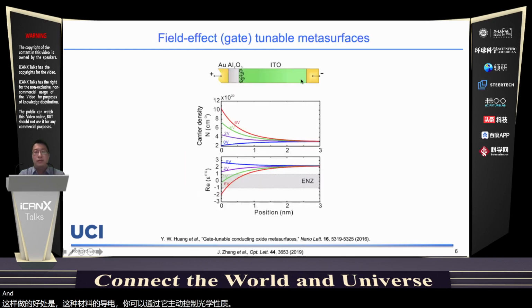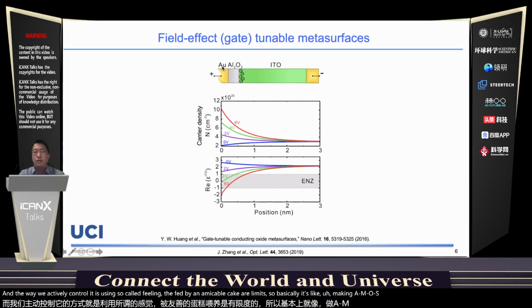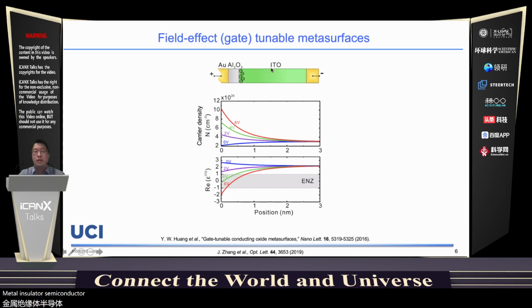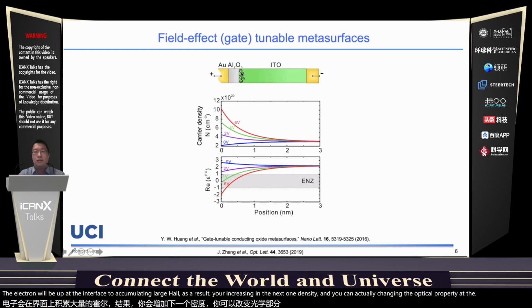And the way we actively control it is using so-called field effect dynamics, or gate dynamics. Basically it's like making a MOS transistor you learn about in solid state physics. You have a metal, insulator, and semiconductor, here indium tin oxide. Now if you apply a voltage, because you have an insulator here, electrons will build up at the interface, you accumulate the electrons. As a result, you're increasing the electron density and you can change the optical property at this interface here.